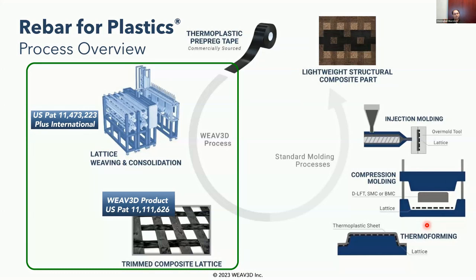But we convert these tapes using a proprietary forming machine into lattice structures, similar to what you see down here on the left. These lattices can then go into conventional plastic molding processes like thermoforming, compression molding, or injection molding. The resulting part is a hybrid of this structural skeleton created by the unidirectional tape and the thickness buildup that you get from the molded plastic part. You can see this in the top right corner, where we have a heterogeneous structure that is 2 different types of tapes.